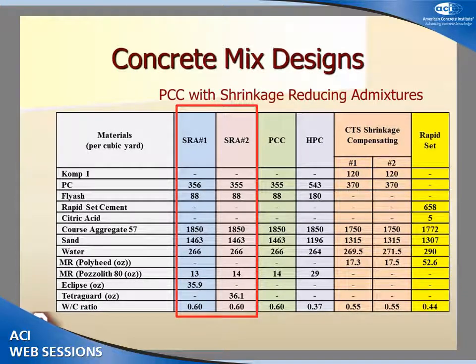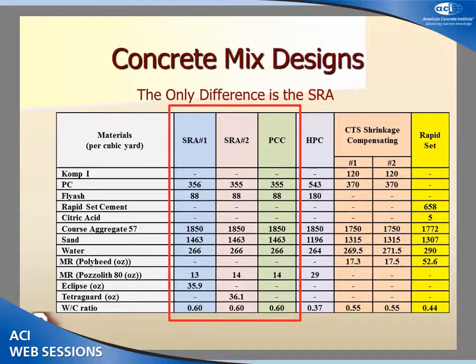2 of the slabs were made with Portland cement concrete and 2 common types of shrinkage-reducing admixtures. We used Eclipse and Tetraguard for our research, and one of the test specimens was made with Portland cement concrete. The only difference between this Portland cement concrete and the first 2 shrinkage-reducing admixture mixes is the shrinkage-reducing admixture. The Portland cement concrete mix is all the same.